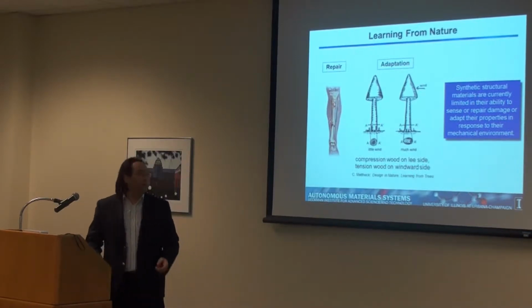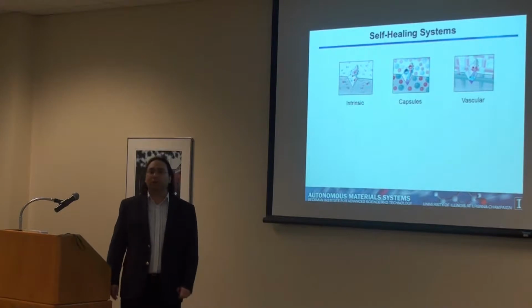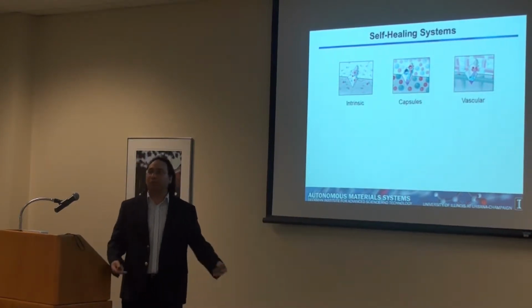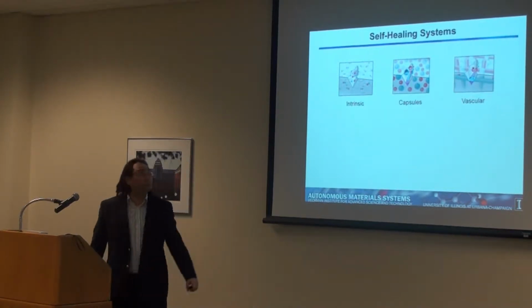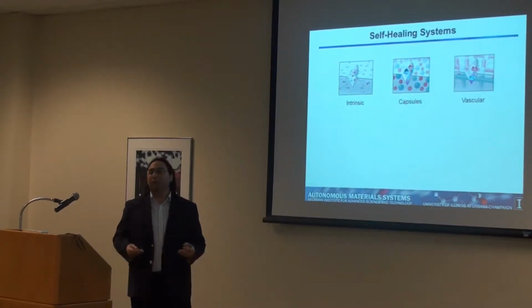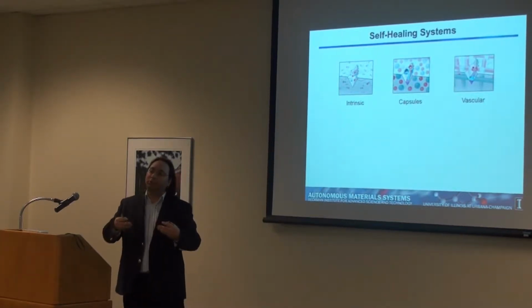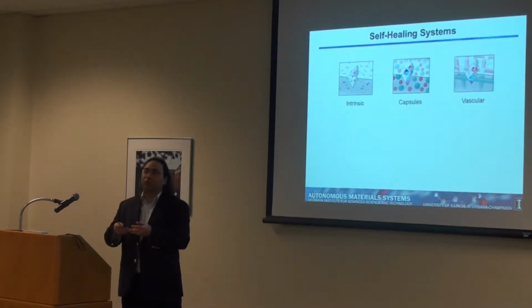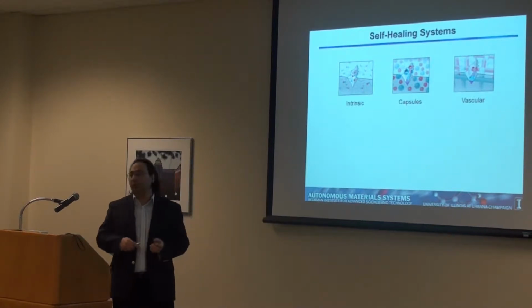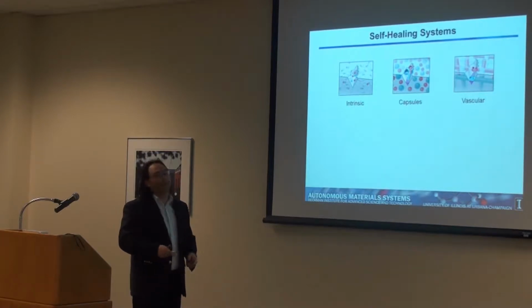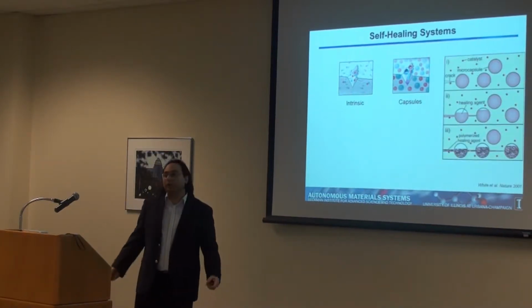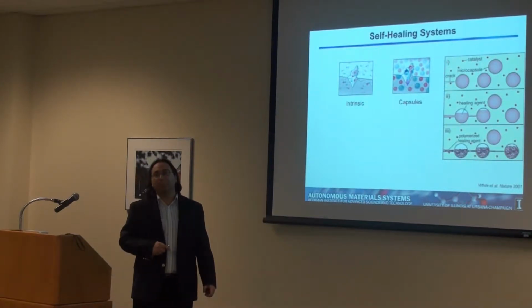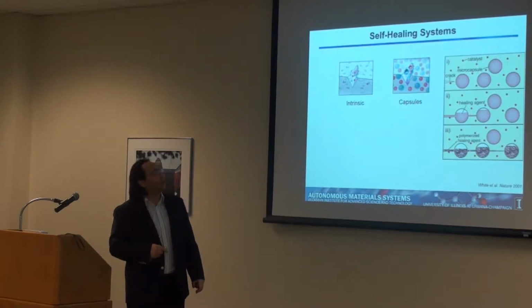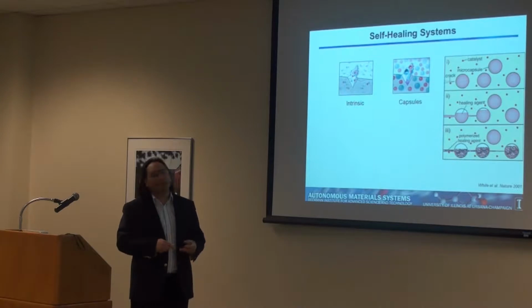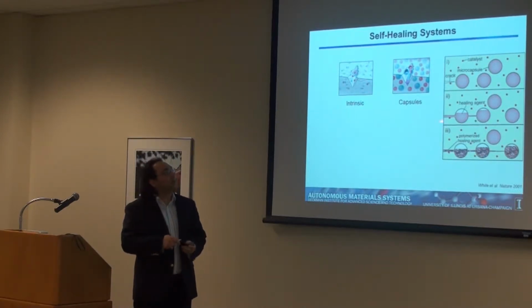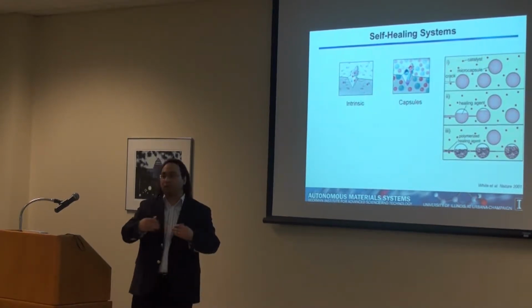So obviously, one of the biggest projects in our group, and one of the coolest ones, is developing self-healing systems, self-healing materials. And we have three different approaches to that. One is called the intrinsic approach, where we basically do a chemical change to the polymer itself, to the material itself, and this small change is the one that adds this feature of healing. I'll talk a little bit about this in a few. The other two methods, which are not intrinsic, are the ones based on microcapsules, and this was published by a group a long time ago. So basically we have microcapsules where you have a monomer inside, for example, and you have the catalyst embedded in your polymer matrix. And when you have a crack, it ruptures these capsules, and the monomer flows into the crack and gets polymerized and closes the crack up.